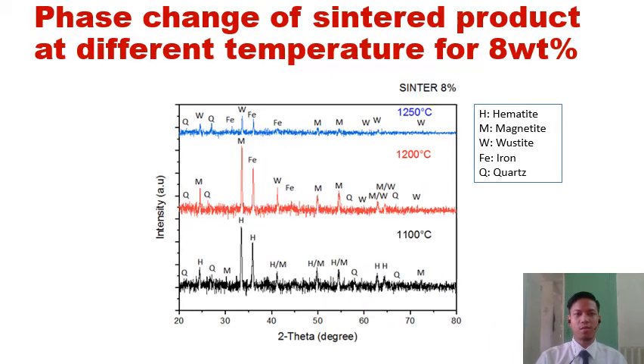And this is the phase change of sinter product at different temperatures for the 8% ratio. As you can see from the peaks, different from the 6% composition, most of the goethite has been reduced to hematite, which makes the major existing phase in the sample at 1100 degrees Celsius consist of hematite, while some of it is also reduced to magnetite, and a slight quartz can also be found.